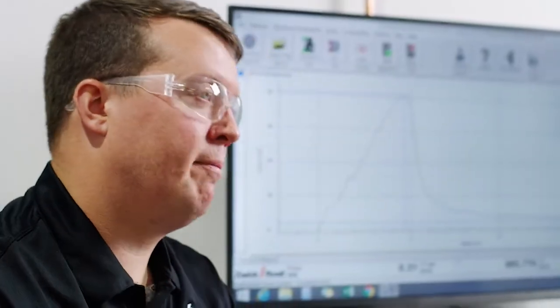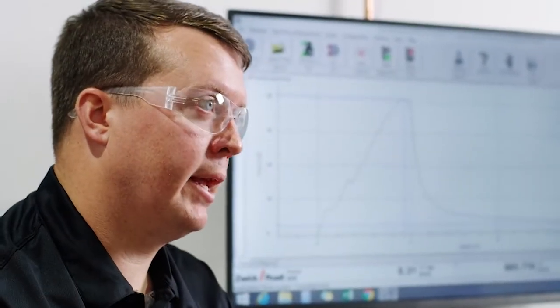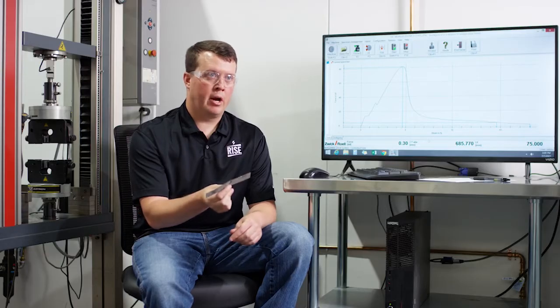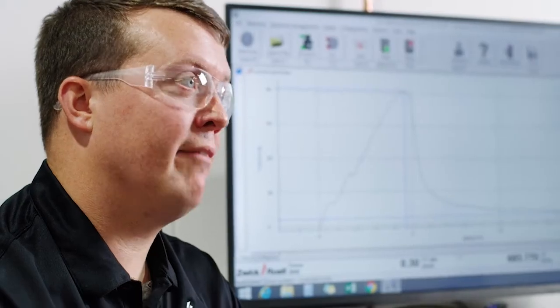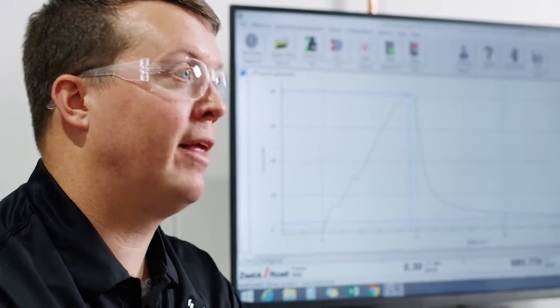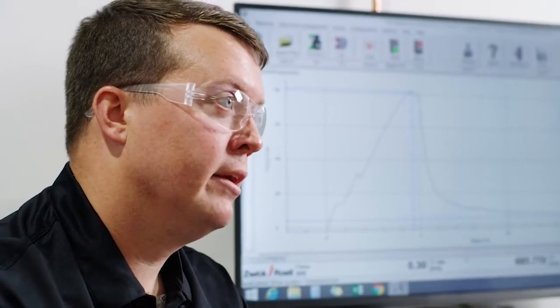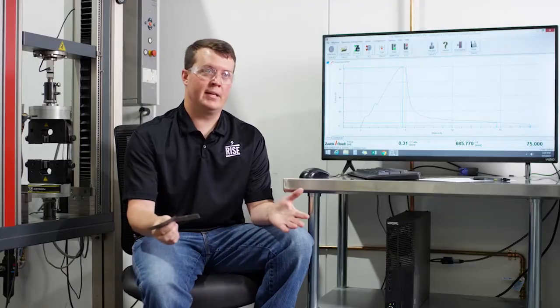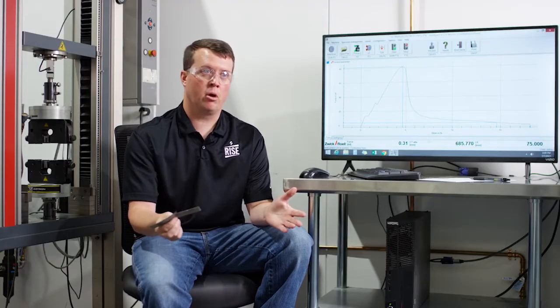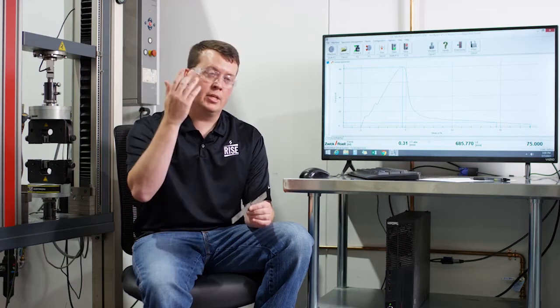If you don't have a high enough polymer load in the beginning, we know it's going to degrade. It's going to degrade quickly, and you're not going to have that polymer to allow for that elasticity throughout the lifetime of that roof. So once you reach around that 10, 15 year mark, you don't have enough elasticity in your blend to overcome that substrate movement, to overcome the movement you have multiple times a day when the sun's at the highest point or when it's cold at night.